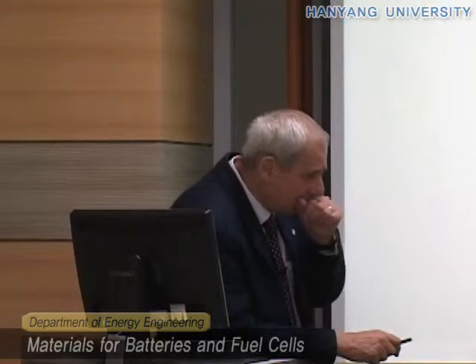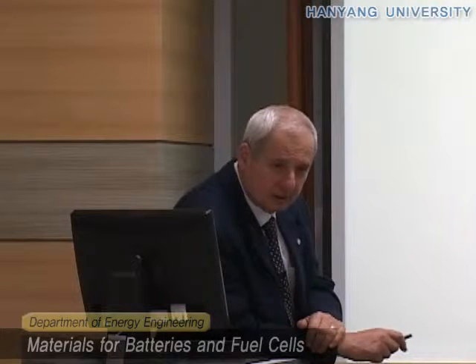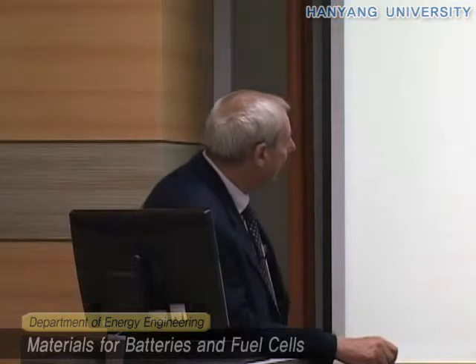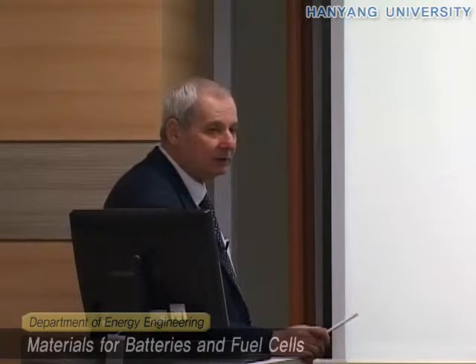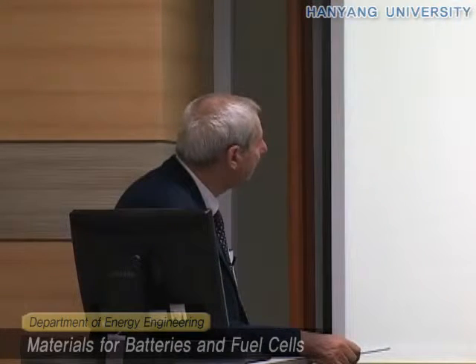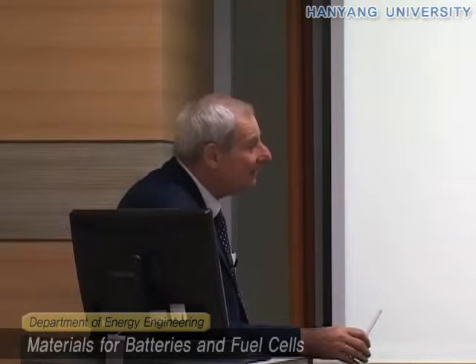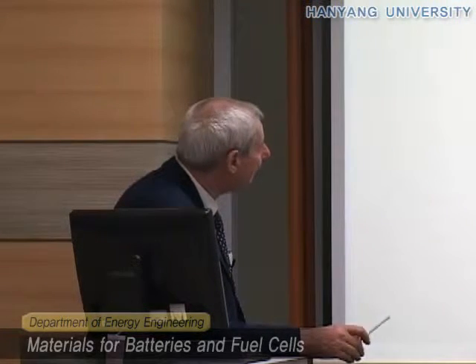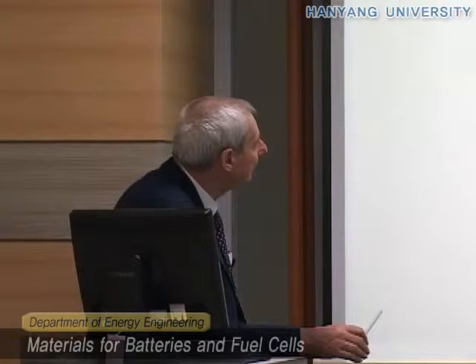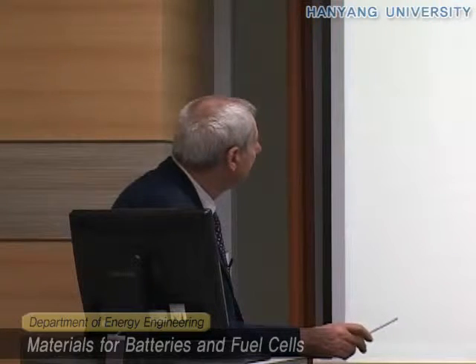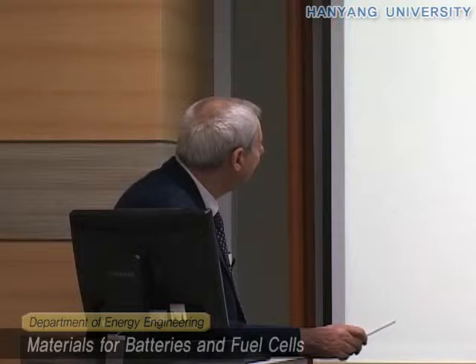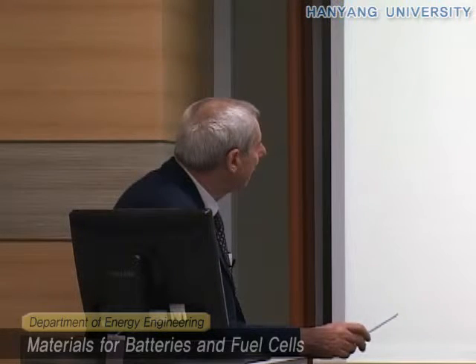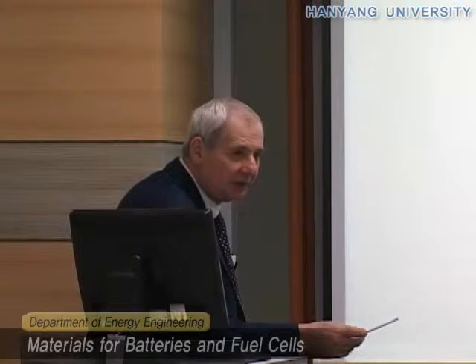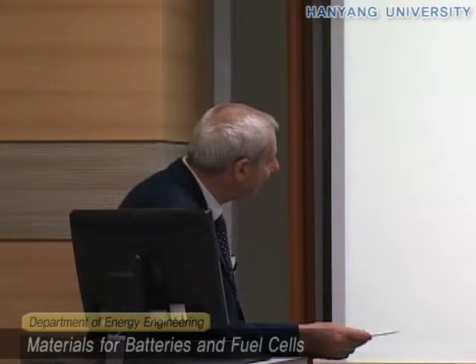I think all the batteries used in iPods use a polymer. And you have two types of polymer. One, used commercially now, is the so-called gel polymer electrolytes. These are not really polymers, but hybrids, in the sense that they are formed by a polymer matrix, mostly polyvinylidene fluoride, PVDF, okay? And this polymer matrix contains the standard liquid solution. So this is not a liquid, because the liquid is inside the polymer cage. It's not a polymer, because there's some liquid. So it's a hybrid system.